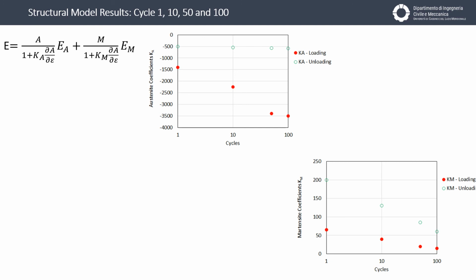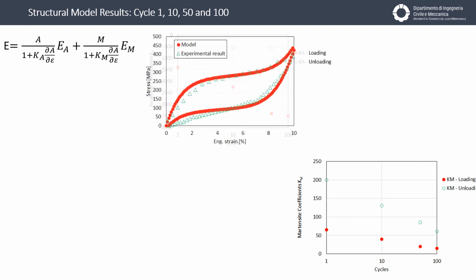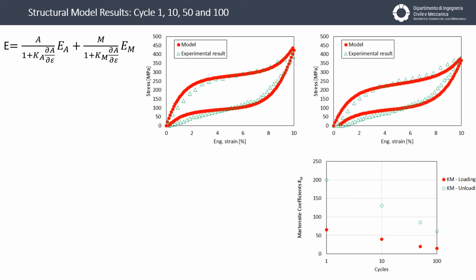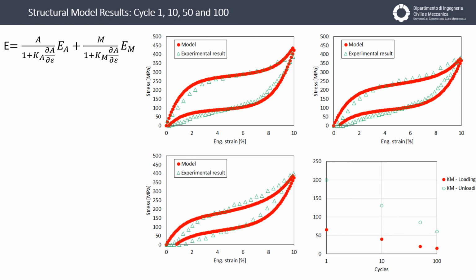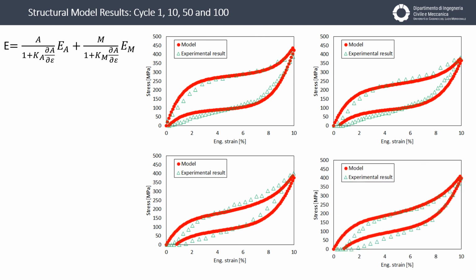This is the formula proposed in this work, and here you can see the stress-strain behavior at the first cycle. We can see that the calculated values seem to fit well the experimental results. In the same way, we can see the comparison between the model and experimental values at cycle 10, then at cycle 50, and finally at cycle 100.